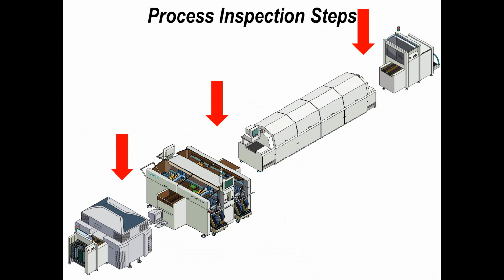So if we were to look at this diagram, I've highlighted the three most common places that people use automatic optical inspection or semi-automatic inspection: after printing, after placement, and after reflow. Now, typically, most companies concentrate their efforts after reflow soldering and after the printing process, and those tend to be the two locations. However, some companies may look prior to reflow as well.